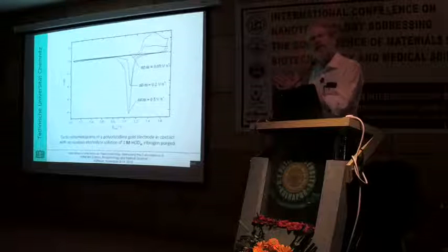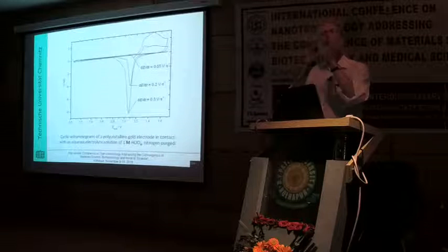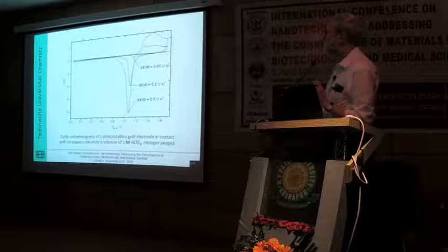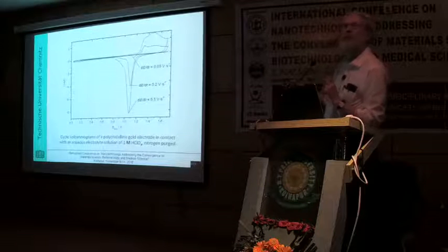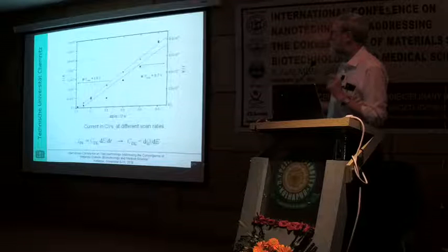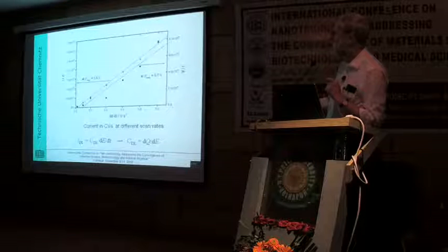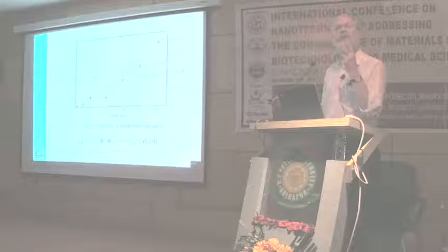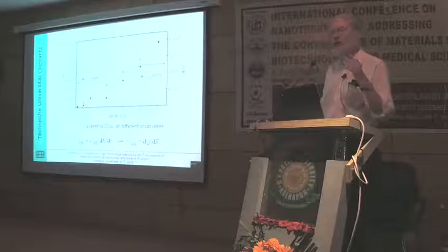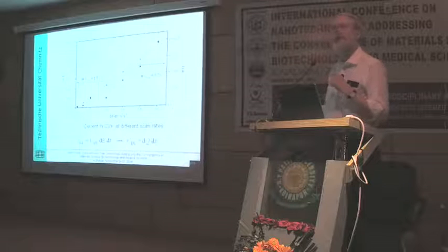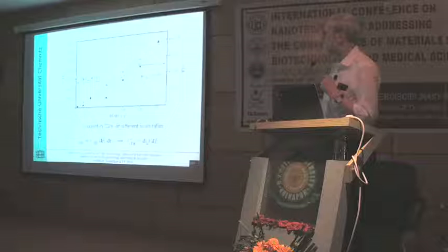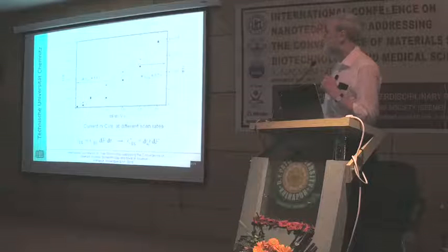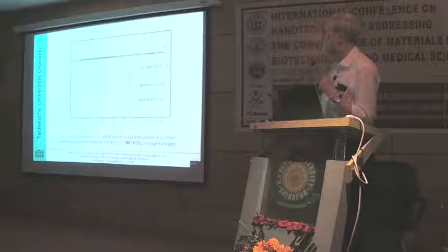This electrochemical interface behaves like a capacitor, two plates and an insulator in between. If we move to more positive electrode potentials, the currents suddenly become much larger. Once again, as a function of scan rate, I have displayed the currents, and now the currents are larger by about 2 orders of magnitude. You remember? In these supercapacitor electrode materials, in electrodes and cells, we can store about 10 or 100 times the amount we can store if we just employ the double layer capacity. And once again, the current increases as a function of the scan rate in a linear fashion.